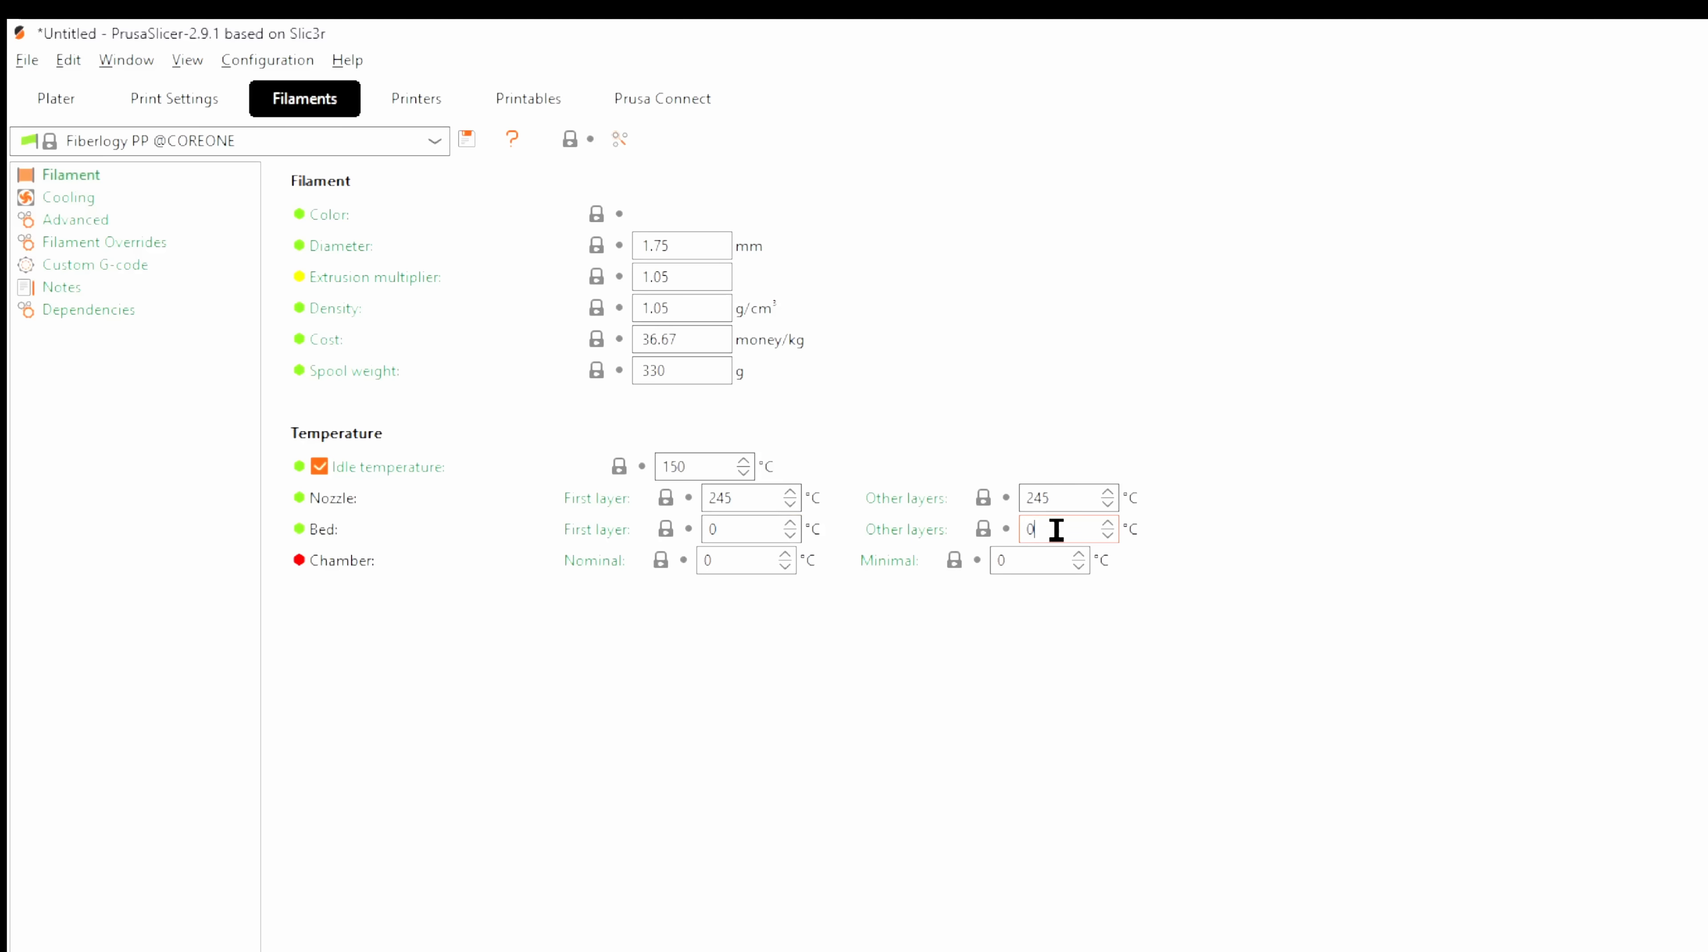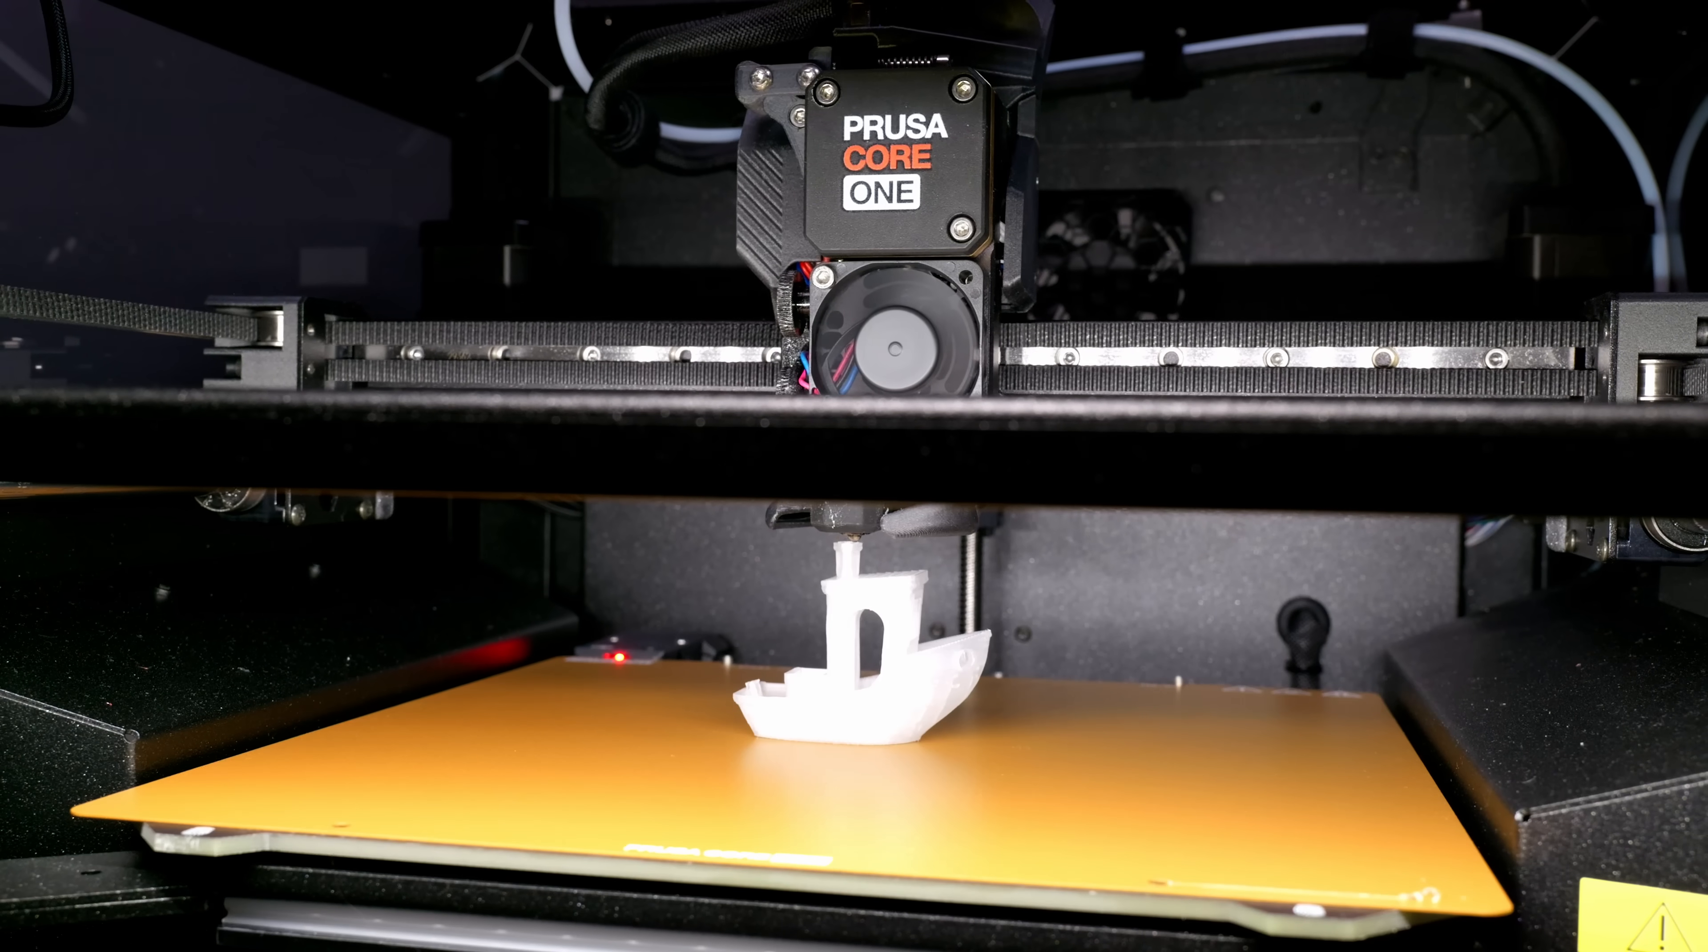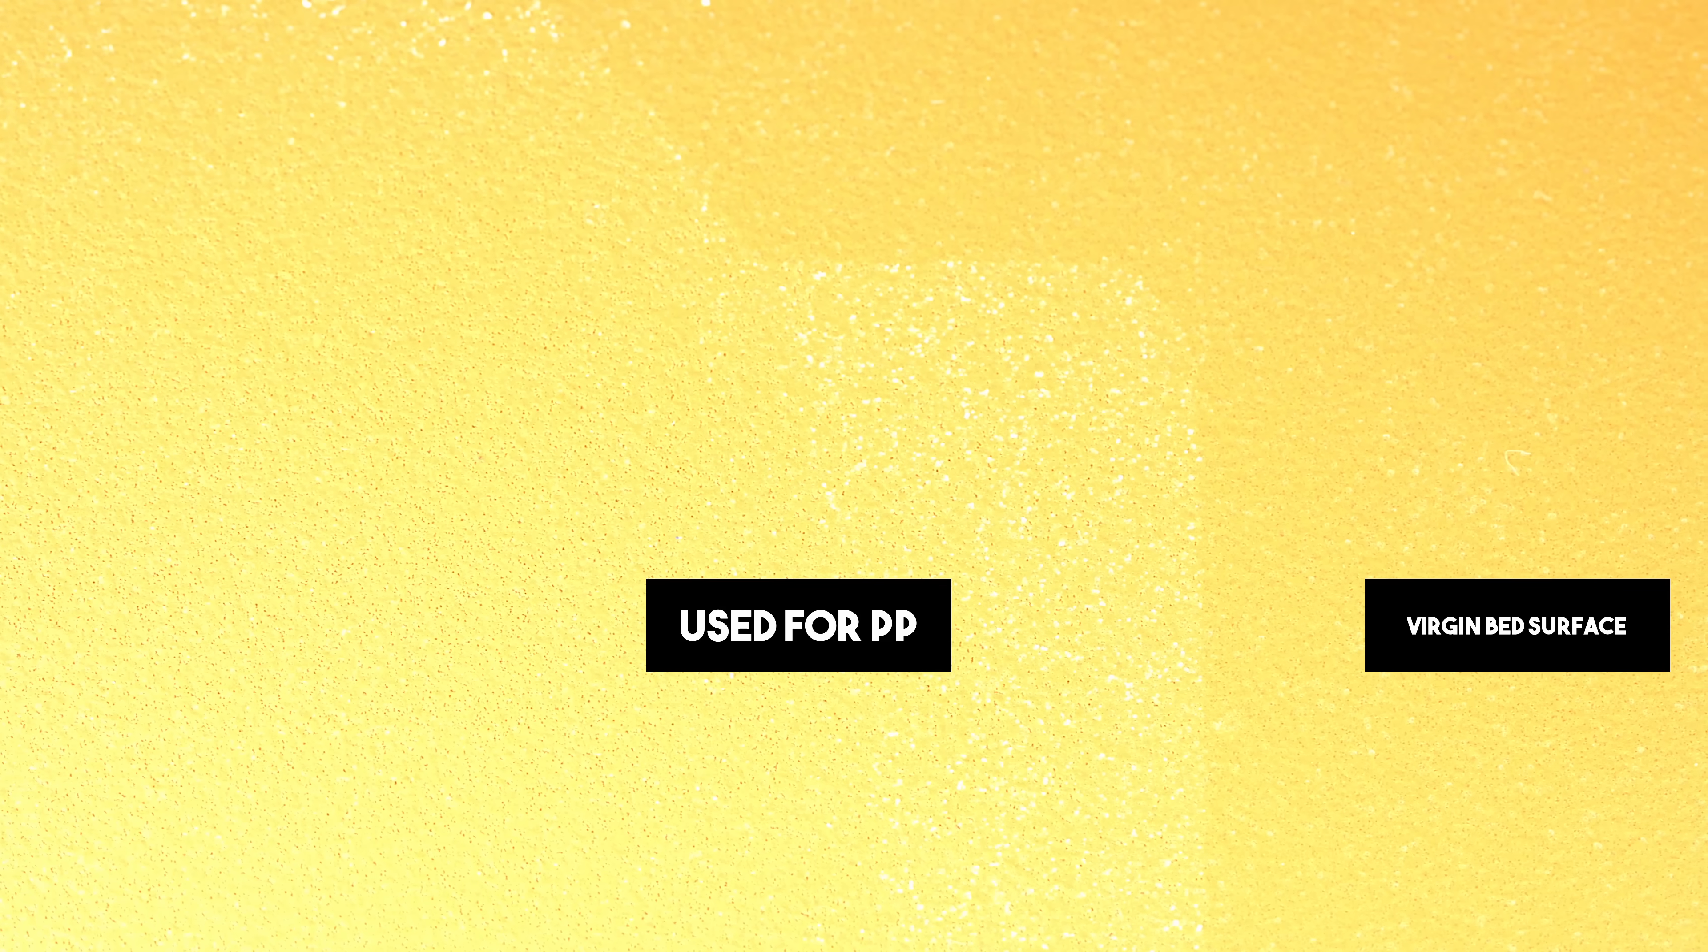The reason though that the Prusa bed wasn't working for me was because this was actually the first test I'd done on the core one rather than the sovol and thus I'd moved over to Prusa slicer instead of orca and for some reason some of the polypropylene profiles on Prusa slicer by default have the bed set to 0 degrees celsius and I have no idea why. As soon as I sorted out this bed temperature problem everything was absolutely fine and the bed works just as well as Magigoo, with the advantage of this being not messy. Not that Magigoo is particularly messy, but you don't have to clean it off put it back on again, you've basically just got the equivalent of a PEI sheet but for polypropylene and that's obviously great. Other than the harmless weird mark that every print leaves on it, it's fully reusable.